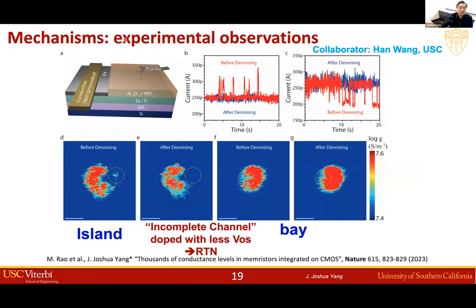Then the question is, what's the mechanism of the denoise? And we use a conducting AFM to help us understand this. The conducting AFM can visualize the conduction channel in the device before denoise and after denoise. For example, before denoise, the device is switched to a fresh state, and we use scanning conducting AFM to look at it. We find that there is a major conduction channel, and next to it, there is an island. This is relatively more resistive, and the total device shows big noise.